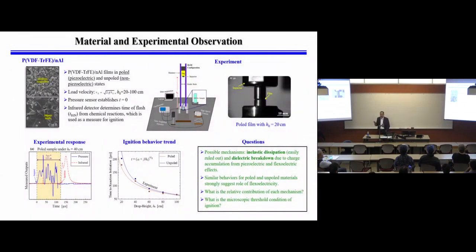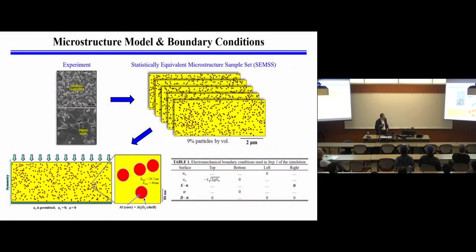And these are the experiments I showed you previously at the beginning. You apply a mechanical force, but the stress generates an E field in the material through piezoelectricity and flexoelectricity. The material model is what I talked about already. We have the aluminum particles, we have the polymer, and our model is pretty similar. But there is also an aluminum oxide layer around each particle. Aluminum is very chemically active. Pure aluminum doesn't exist in air. It has an oxidized layer, so that has to be considered as well.